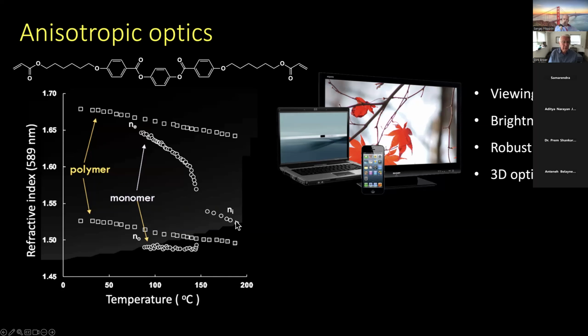Well, as soon as you start polymerizing this sample, you keep the optical anisotropy, but then the temperature dependence becomes basically far less. Still a minor change because of the volume expansion coefficient, but much more stable than that of low molecular weight crystals. And for that reason, the material became actually of interest for the upcoming display market at that time. Liquid crystal displays were developing, they were improving and improving, but still had a number of problems to solve. The viewing angle was not always right, the brightness was not always correct, they were not so robust.